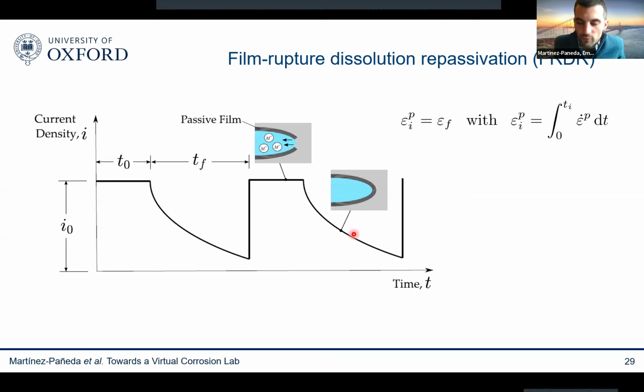So what do we do when we have corrosion problems? We use corrosion-resistant materials such as stainless steel. And then what will happen is that you will generate a layer that will protect you from corrosion, but this passivation layer is ruptured due to mechanical straining, and then you enable localized corrosion, pitting, and stress corrosion cracking. And this is, of course, a challenge. How to predict when the layer is going to rupture and we're going to have this localized corrosion phenomena. And we know what happens quite well.